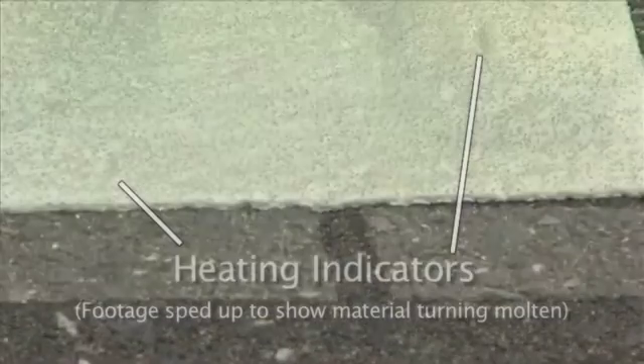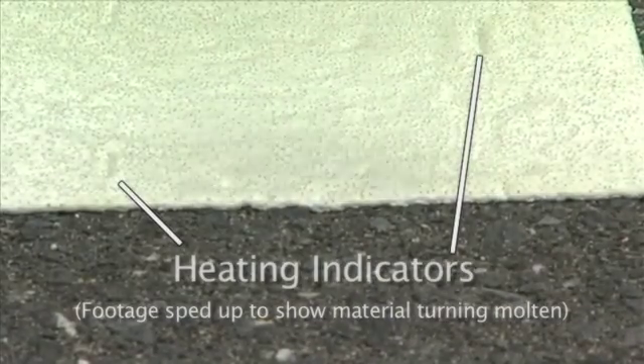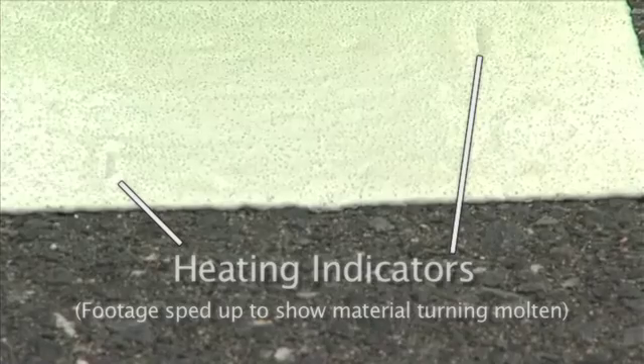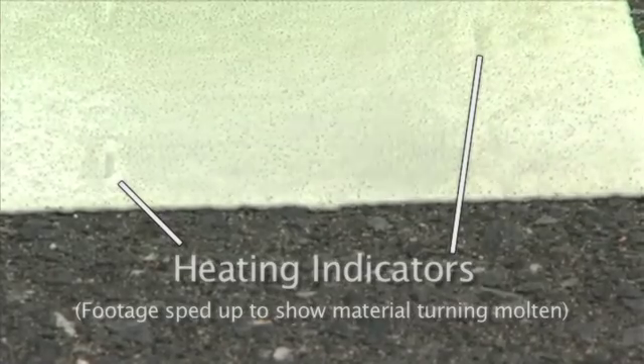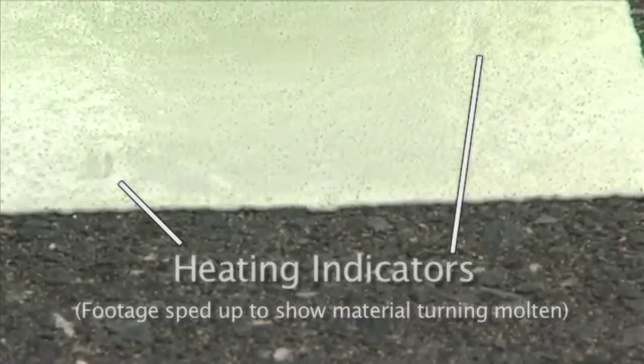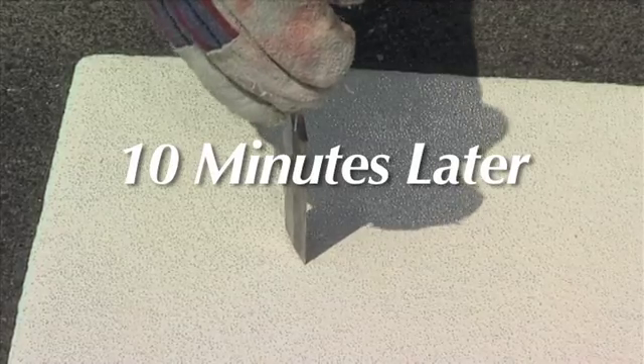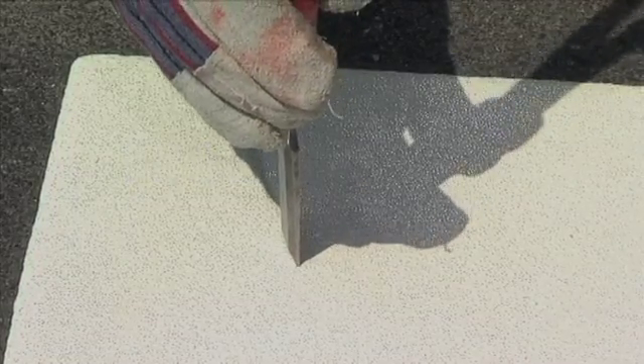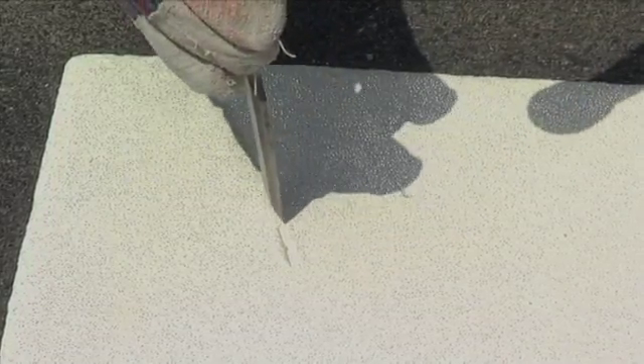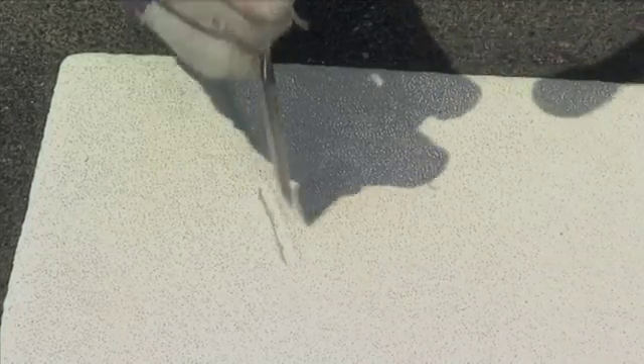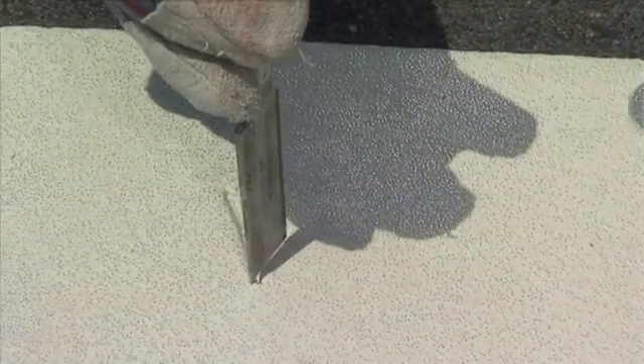The indents are heating indicators that provide a visual cue during application that the material has reached a molten state for satisfactory adhesion and proper bead embedment. The material was allowed to cool for approximately 10 minutes. In order to determine bond performance, a chisel test is performed on each product. First, we will test the no preheat product on the left.